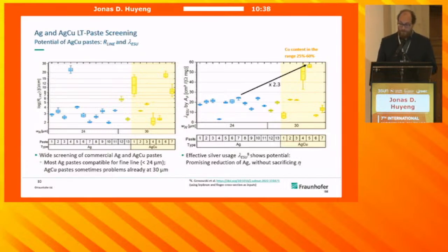but there's also some very good examples here that have pretty similar results in terms of that metric. And then you can convert this thinking about, because you're still using silver, how effectively are you using the silver to get resistivity reduction in your line width? And this is what this lambda ESU parameter is telling you.